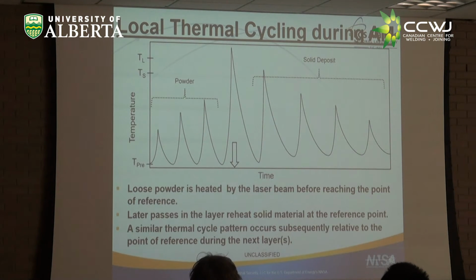The local thermal cycling is like a multi-pass weld. So here is my location that I'm going to reference. If I think about time versus temperature, this is the preheat temperature, this is the solidus, this is the liquidus. Obviously, to melt, I need to go above that. But as the beam approaches during the rastering process, the powder, which is just sitting there loose initially, will see several thermal cycles, then the melt and resolidification cycle, and then several other cycles afterwards where it's solid. This is where the heat affected zone will form in the prior layers. So we need to bear this in mind also, and that was an important thing we talked about a little while ago with the other two heat affected zones.